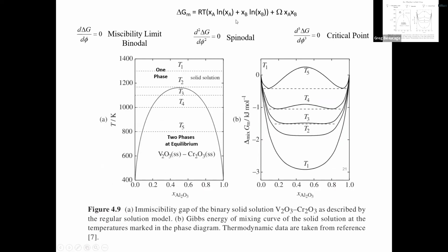So this is the entropic mixing of kind of marbles. Basically, you have red and blue marbles. That's the entropy of mixing times temperature, which gives you the free energy. And you add in an enthalpic term that's binary interactions between the A and B units. This has the average energy of interaction between the A and B units, defined exactly the same as in the Flory-Huggins. So that should be something like committed to your memory. That's for mixing of anything.